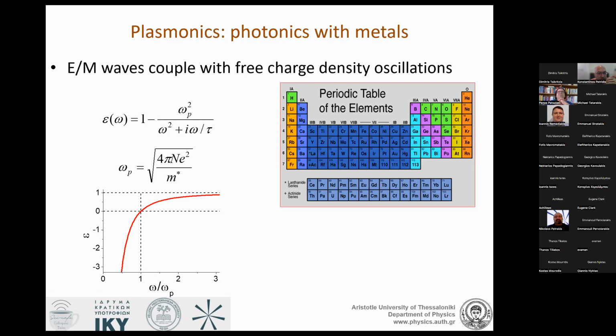What are plasmonics? Plasmonics actually are photonics with metals, or conductors in general, because, as the title of my talk says, the metals can also be ceramic conductors. So the electromagnetic waves couple with the free charge density oscillations because of the free carriers in the conductors. That means we have an epsilon1, the real part of the dielectric function, that is negative up to a certain value, which is called the plasma frequency, and then gets a positive value. And this crossover frequency or crossover wavelength is roughly where the plasmonic phenomena will occur.